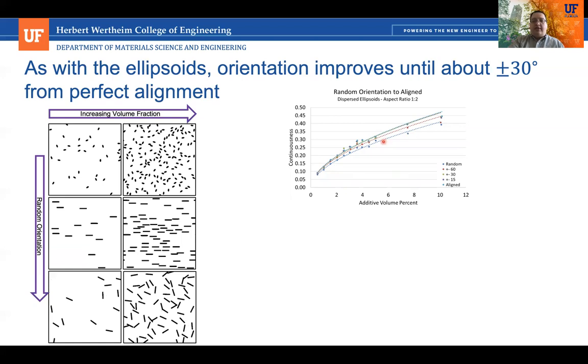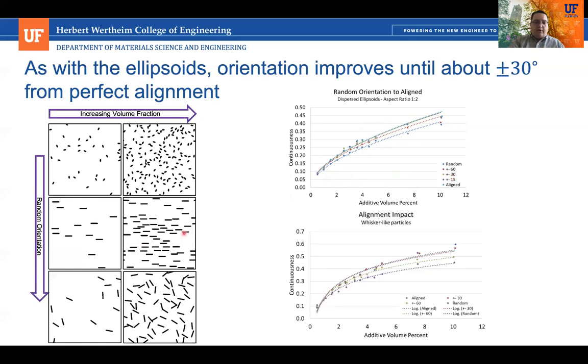But then as we align them more and more, it starts to improve, but it eventually stops improving. We get to the point where even additional alignment does not significantly improve the thermal conductivity. And that happens at about plus or minus 30 degrees. And when we look at the rectangular particles, we see the same behavior, that as we go from random to 60 degrees, we get a large benefit. And then when we go up to 30 degrees, we get a benefit. But as we go up to 15, there's no additional benefit. So again, 30 degrees is about the best we get, even when it's compared to fully aligned microstructures.